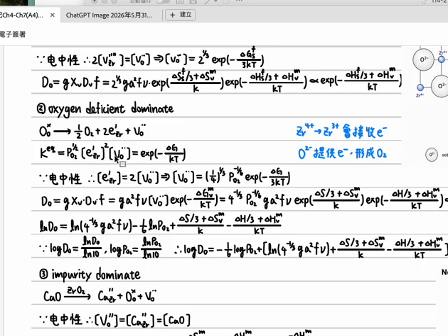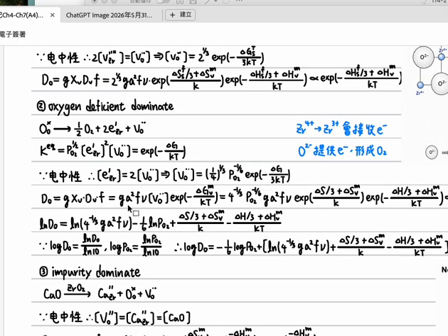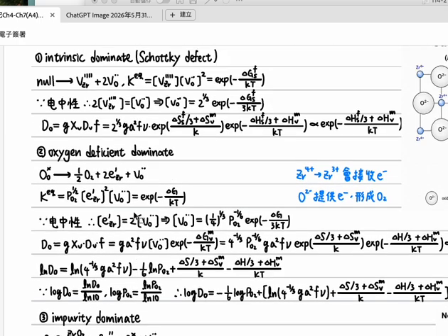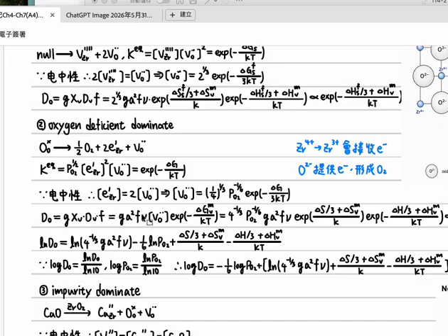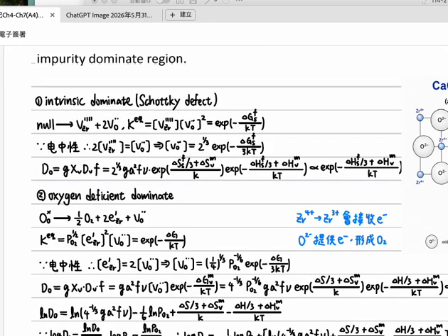And solve for VO, so I will get this result. And this substituted back to here, so I can get the D0. Because this is a VO, then XV here, substitute this term. And the rest of the part will be the migration term, a squared f nu. This will be the migration, dV. And put G here because it's ionic materials. It's double FCC. This is G, the geometry factor. Okay, so this is for your reference.